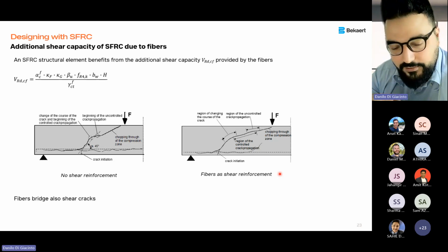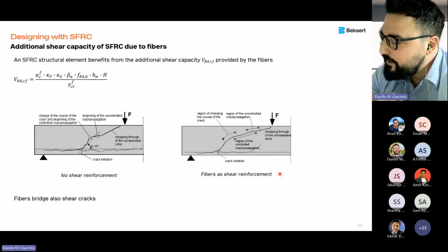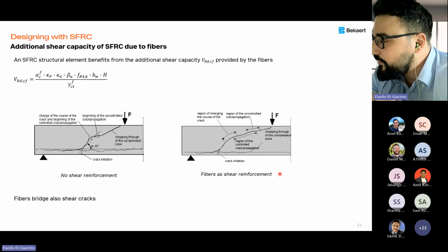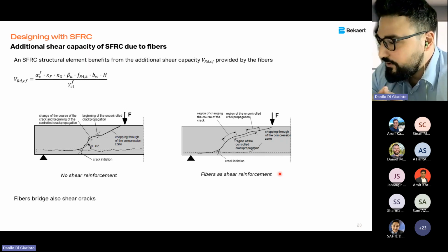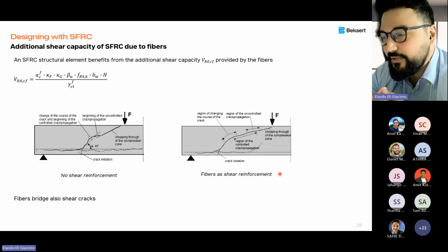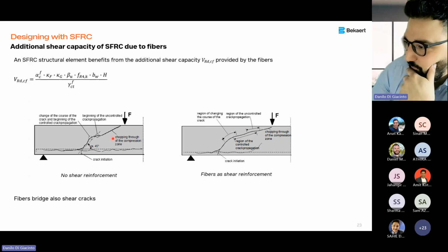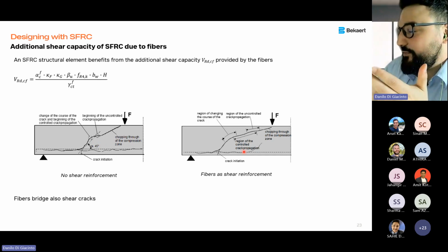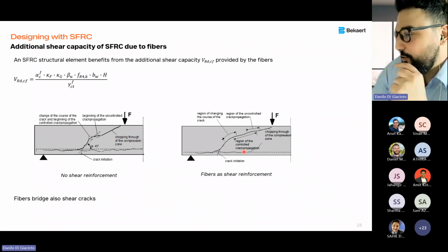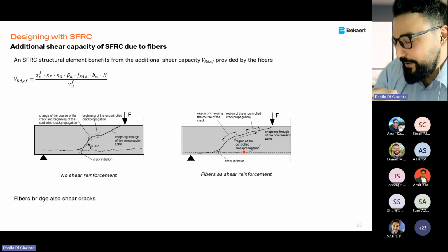For shear, it is even more intuitive to use fibers, because shear is a brittle mechanism. When you use fiber, you have a ductile mechanism for shear. You can avoid using transversal reinforcement, and fibers can also bridge shear cracks. Here, for example, with no shear reinforcement, you have a narrow cracking path, while here you have a wider cracking path with smaller cracks and a controlled mechanism. So this structure reinforced with fibers is more ductile than this structure with no shear reinforcement. You can achieve something like that with stirrups, for example, but with fibers you can achieve both flexural and shear capacity at the same time with the same material.